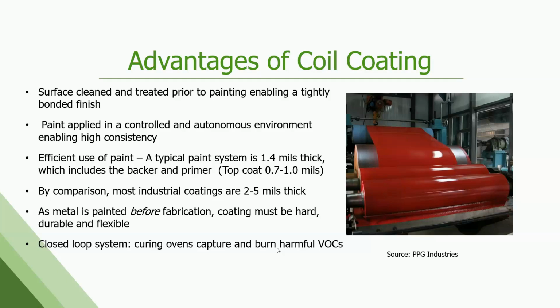By comparison, most other industrial metal coatings, like for cars, powder coatings are 2 to 5 mils in thickness, so we're using a lot less paint. There are solvent-based paints, but we are capturing those solvents as they go through the ovens and using that heat in a closed-loop system, so the final product is VOC-free. And again, this all happens before the fabrication, roll forming or stamping, whatever's going to happen to this metal. So this paint has to be very thin, it has to be hard, but also very flexible, and it's got to last on the outside of a building for 20 to 50 years without any change.